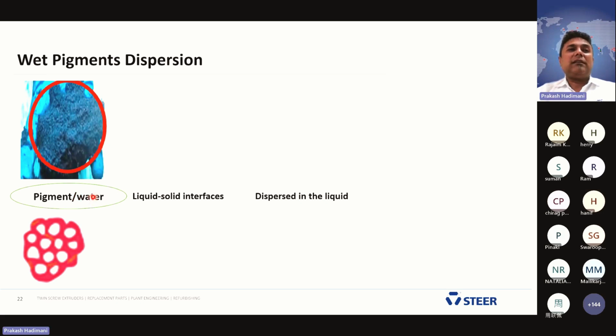60% of the water and the remaining 40% pigment. What is going to happen here? It's easy to disperse because this is your pigment, and this is the water surface on the outside. When the pigment is in the water media, it's a liquid-to-solid interface, and when you disperse the particles, they will not form agglomerates.